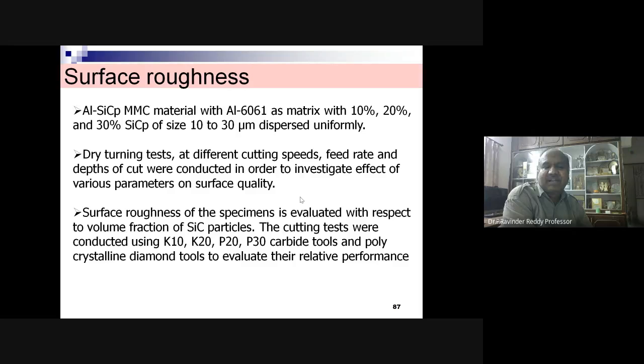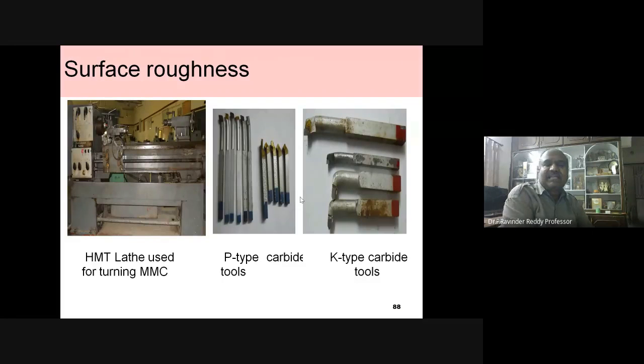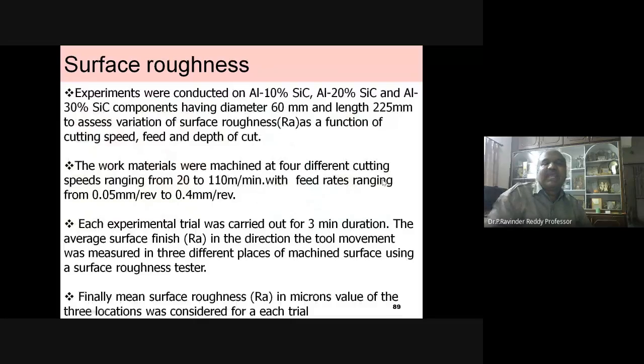The cutting tests were conducted using K10, K20, P10, P20, P30 carbide tools and the polycrystalline diamond tools to evaluate their performance. The surface roughness, this is going to be the later mission. The P-type tools and K-type tools showcased, and the results obtained are shown. The work materials were machined at 4 different cutting speeds, ranging from 20 to 110 meter per minute, with feed rates ranging from 0.05 mm per revolution to 0.4 mm per revolution.